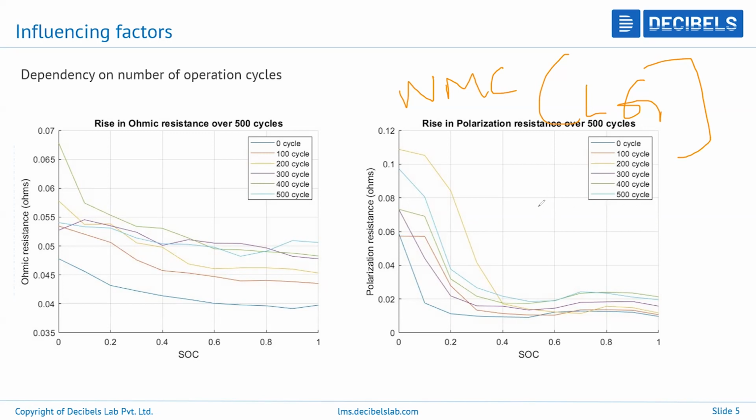Here a 2600 mAh cell was tested up till 500 cycles, and it was depleted till the point where the resistance achieved this value, and it was no longer able to give the capacity as expected. At the end, the capacity achieved something like 1850 mAh.